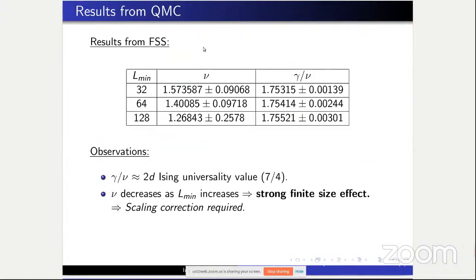Now the results from finite size scaling analysis. What we have done here, we have gradually discarded the smaller system sizes and obtained the values of nu and gamma by nu to see the finite size effect on the result. And here L min equals 32 means we have taken system size 32 and the higher system sizes, and similarly L min equals 64 means we have taken system size 64 and the higher system sizes, and obtained the result.